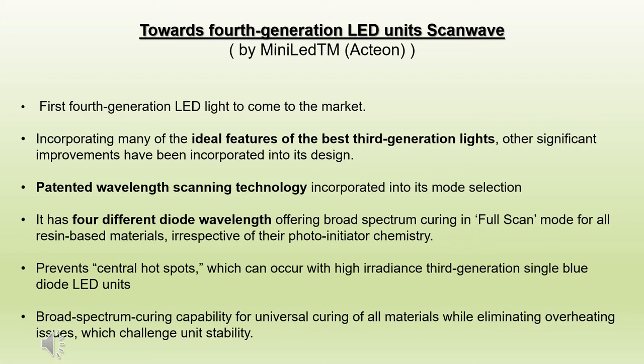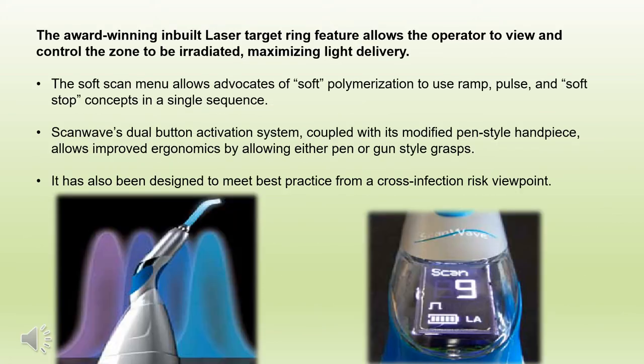By sequencing the activation of the different wavelength diodes in scan modes, the manufacturer has integrated broad spectrum curing capability for universal curing of all materials while eliminating overheating issues which challenge unit stability. The soft scan menu allows advocates of soft polymerization to use ramp, pulse, and soft stop concepts in a single sequence, optimizing cure while negating high stresses possible with bulk polymerization of fast-setting high-modulus materials and thermal stressing caused by sudden light cessation. ScanWave's dual-button activation system, coupled with its modified pen-style handpiece, allows improved ergonomics by allowing either pen or gun-style grasps. It also has been designed to meet the best practice from a cross-infection risk viewpoint.